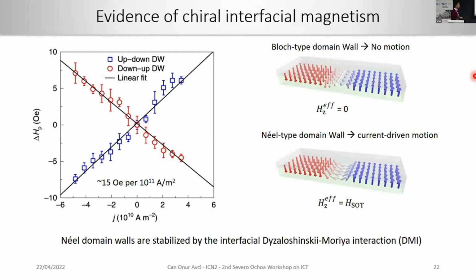This was a surprise for us because typically in a magnetic material, magnetostatically, domain walls are of what's called Bloch type, which means you have an up and down magnetization domain, and going from up to down, it will rotate like this. But due to the chiral Dzyaloshinskii-Moriya interaction that we discovered at the interfaces of this thulium iron garnet, it turns out that the domain walls are Néel type, meaning that it just rotates like this. So this is the current line, and this is the rotation of the domain wall. And this is very important because otherwise you don't have any effect of the spin-orbit torques on the domain wall.